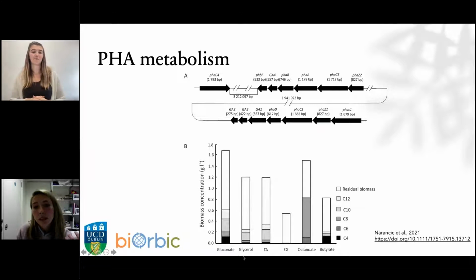And we looked at different carbon substrates, such as gluconate, glycerol, terephthalic acid, ethylene glycol, and many others. And we have shown that depending on the choice of the substrate, you can tailor the composition of PHA. And that is very important. I have also mentioned that polyhydroxybutyrate is very brittle, and I don't have it here, but it looks like a polyethylene bag, but when you apply a little bit of force, you can rip it easily. And then I did mention that medium chain length PHAs can be more rubbery, and the longer the chain is, they become more oily. So you can imagine if we can find a satisfying composition of these monomers, and we create, let's say, a blend between these monomers, we can create materials that have specific properties, and we can then push them down towards specific products.